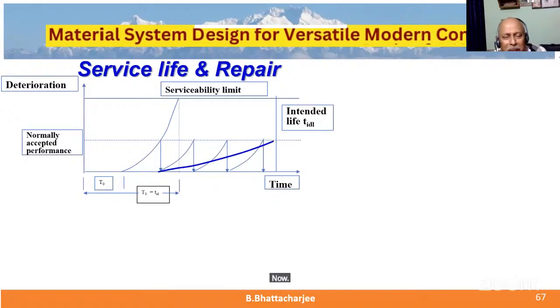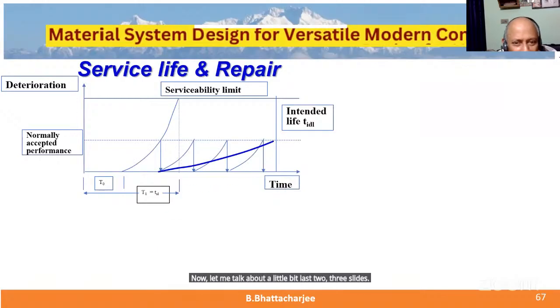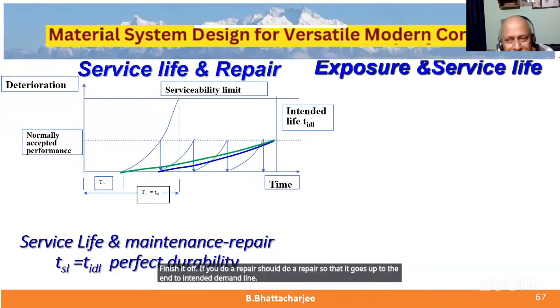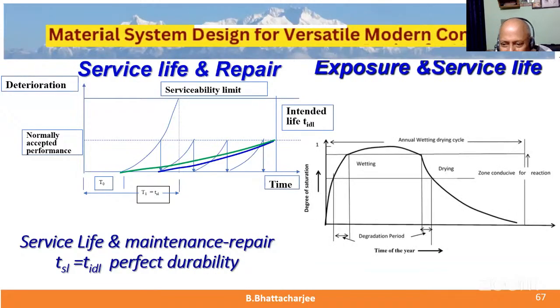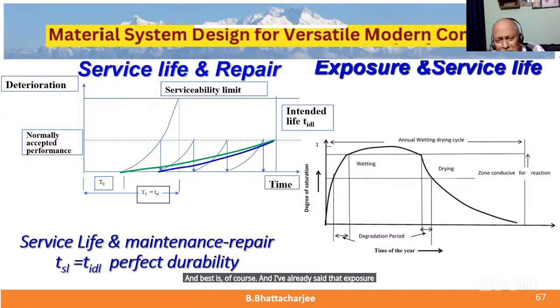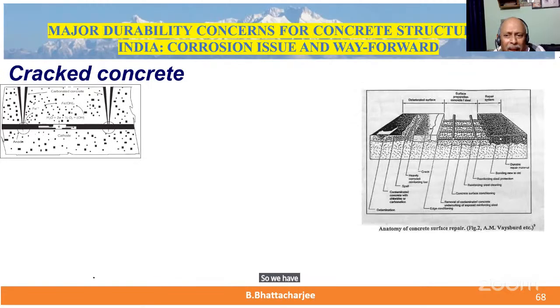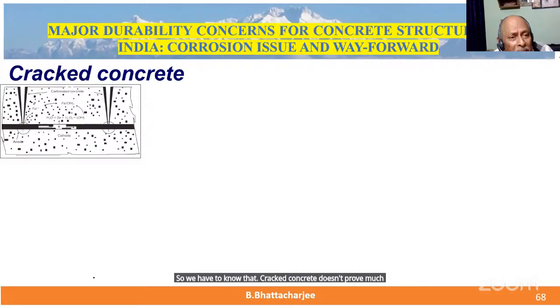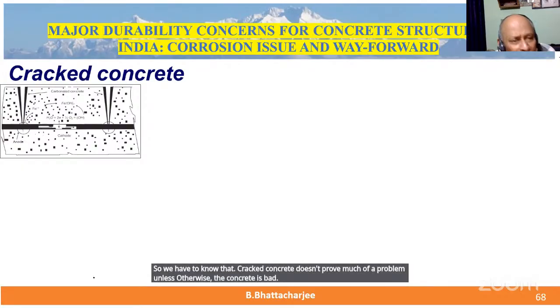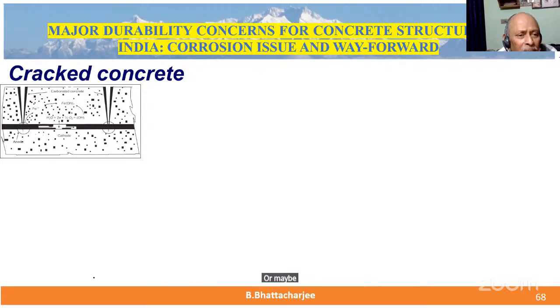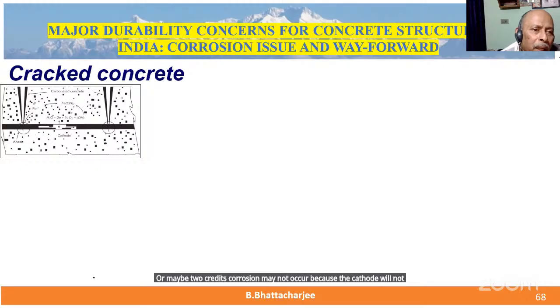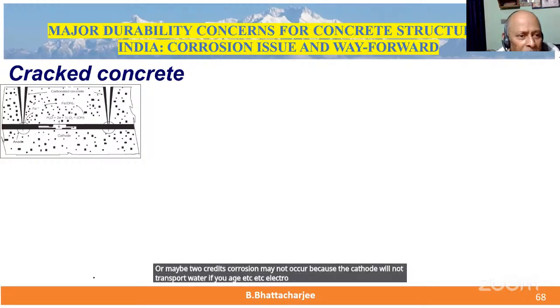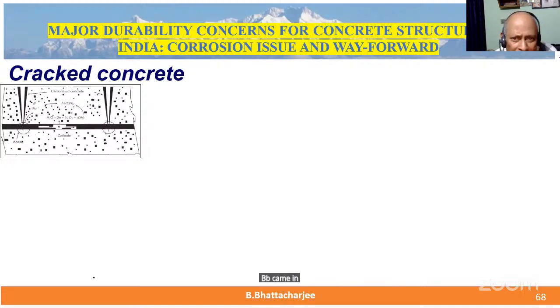Now, let me talk a little bit about the last 2-3 slides, and finish it off. If you do a repair, it should go up to the intended design line. And I've already said that exposure and service life degradation period is small. So we have to know that. Cracked concrete doesn't pose much of a problem unless the concrete is bad. It's an isolated crack or maybe two cracks. Corrosion may not occur because the cathode will not transport water, FeOH, etc. Electrolytic situation in the cathode area will be low. This has been shown by BB doing an experiment in laboratory in the 1990s or 80s, published in the Institution of Engineers Journal from England.